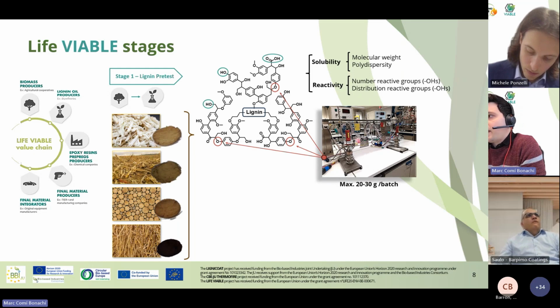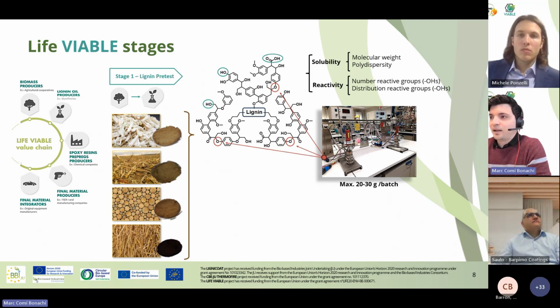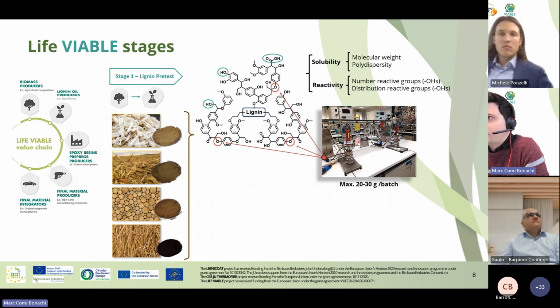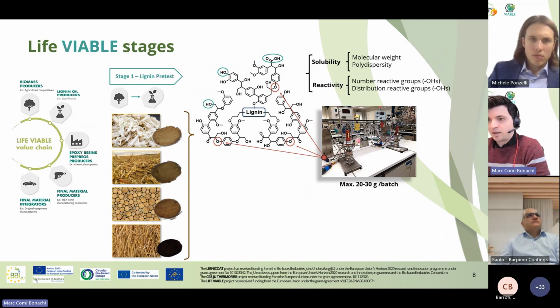So what we do is, at the first stage, we start at lab scale with batch reactors. What we are doing is a reductive catalytic depolymerization, and we are targeting mainly these ether bonds that are in the lignin, these beta-O-4 ether bonds.